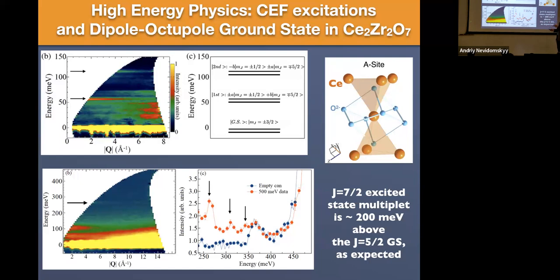So it's J equals 5/2, so it's 2J plus 1 fold degenerate in the absence of a perturbation. That's 6-fold degenerate, and it'll break up into these 3 doublets, okay? And it's basically this effect here. It's the cerium 3+ ion, right, that's sitting in the middle of this slightly distorted cube of oxygen 2- ions, and the oxygen 2- ions are very close. Actually, they're a couple of angstroms away, okay? And that produces these splittings that are of order, in this case, 55 meV, okay?